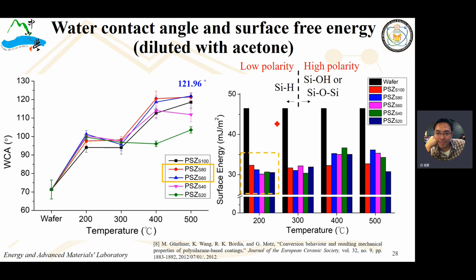I just show you that when we dilute the polysilazane precursor by acetone, we find out that its contact angle increases at 400 and 500 Celsius, and it almost reaches